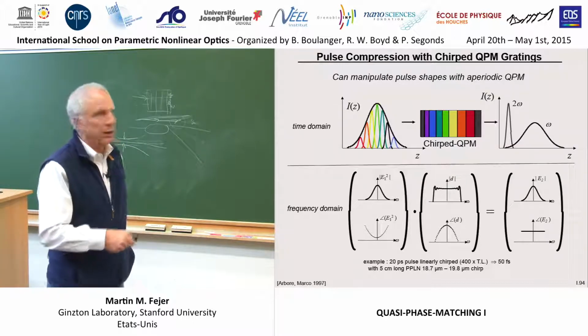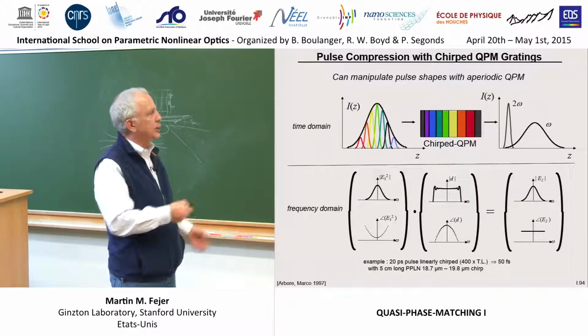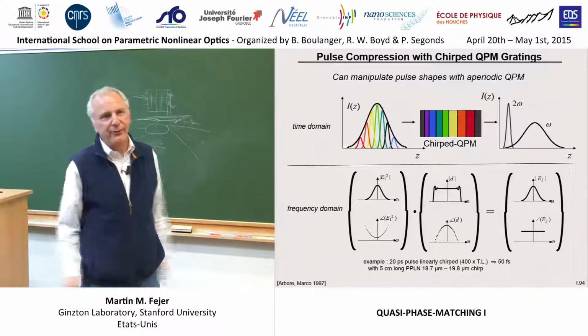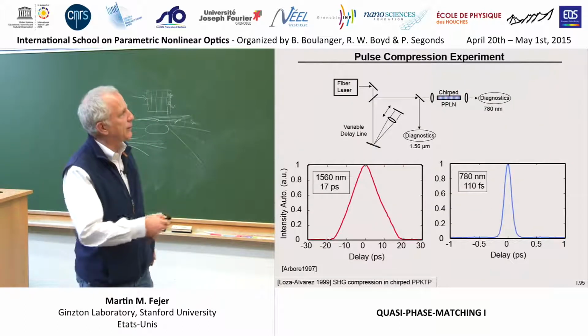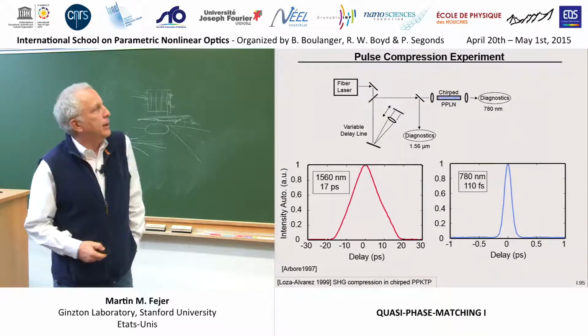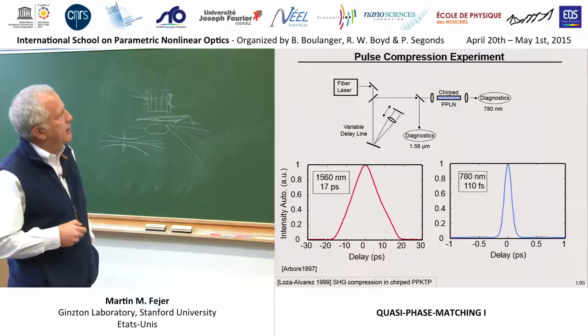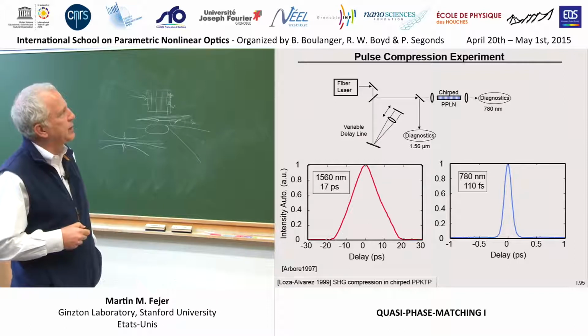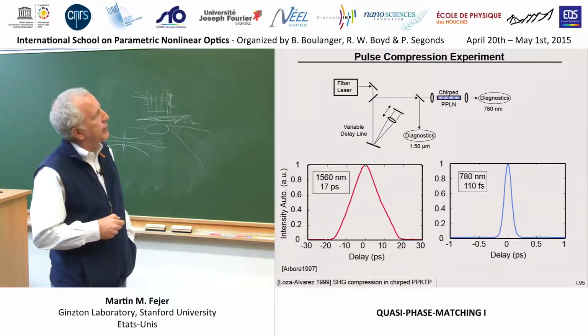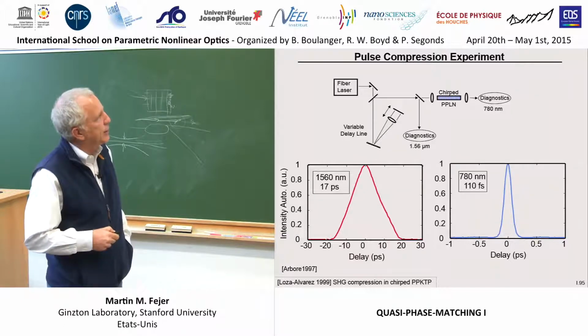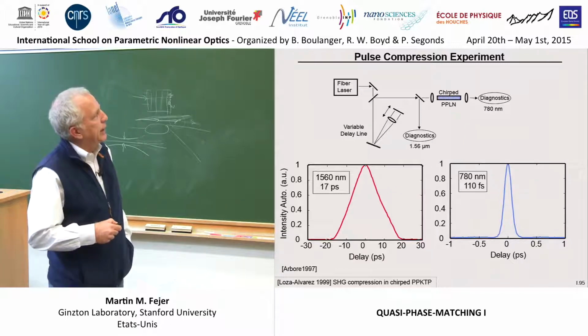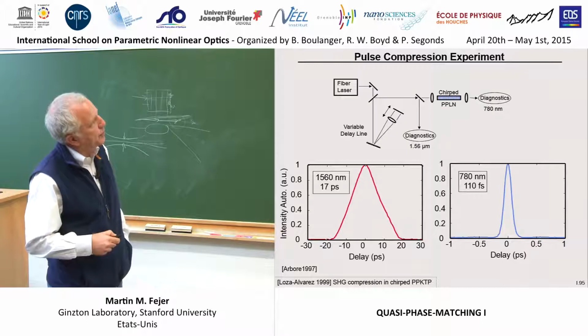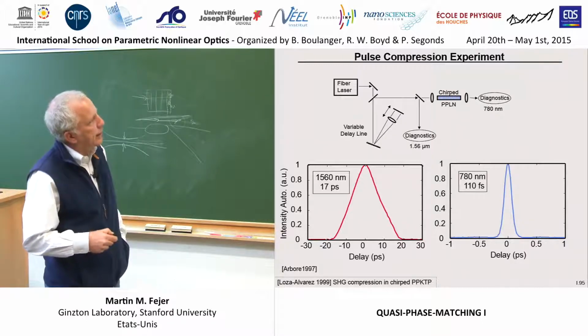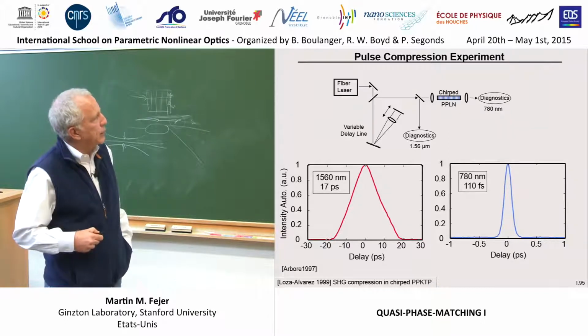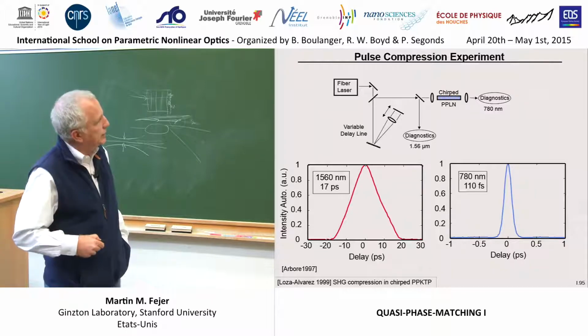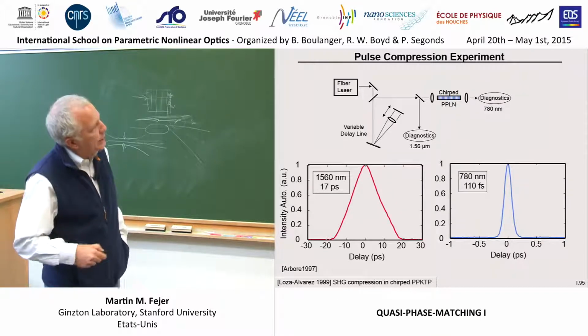This gives you something in many cases a little easier to design for. If you had some cubic phase on this stretched pulse, you could put some cubic phase into your chirp function as a function of frequency. So you have great freedom to design the transfer function of the chirp. So if we look at an experiment trying to demonstrate this, this was about a 100 femtosecond or 120 femtosecond 1.5 micron erbium fiber laser. It goes into a dispersive delay line and is stretched, in this case to 17 picoseconds. That stretched pulse goes through such a chirped periodically poled crystal, and the output is analyzed. And what you find is, if you adjust this correctly, which in this case is 17 picoseconds of group delay dispersion across the pulse, when it comes out as second harmonic, it's 110 femtoseconds.